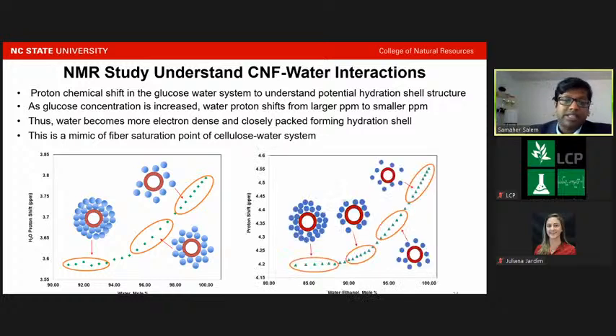We also did the same study, but using a water and ethanol mixture. And we could find that the proton shift follows a similar trend, but the proton shift was higher for the water-ethanol mixture compared to the water. And at the saturation point,